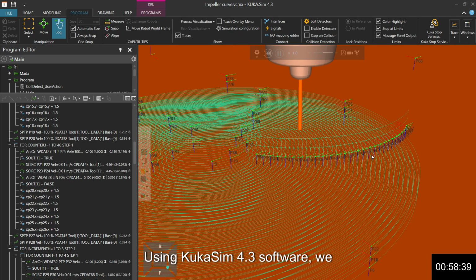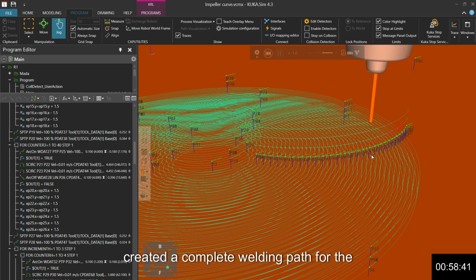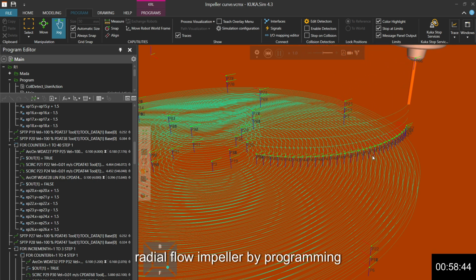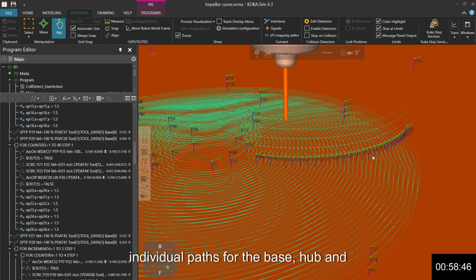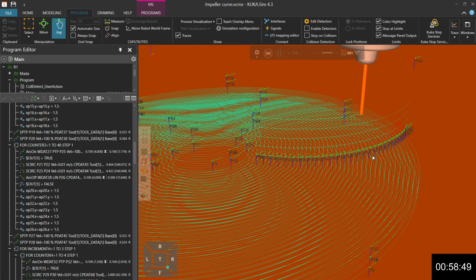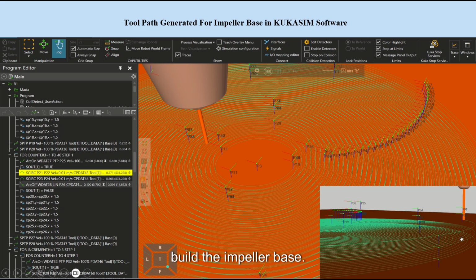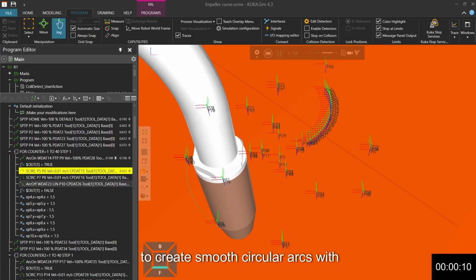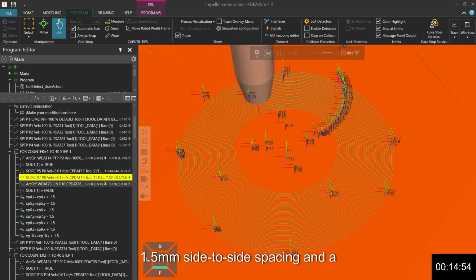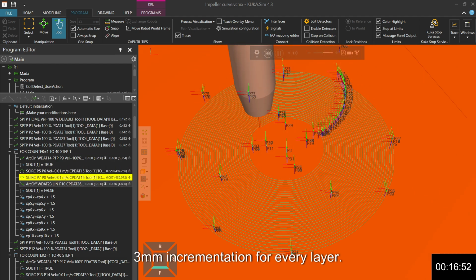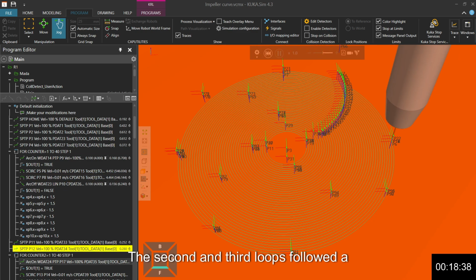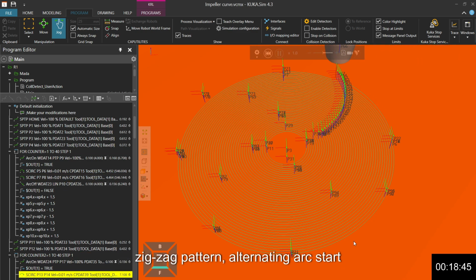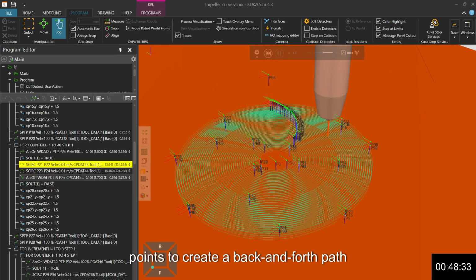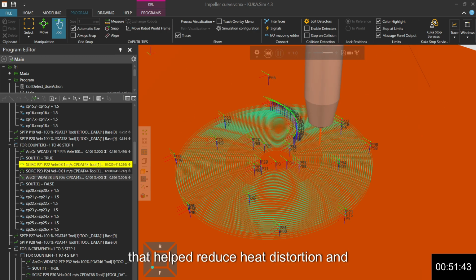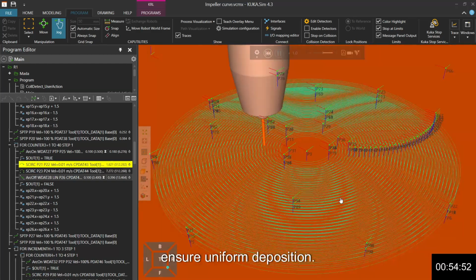Using KUKA Sim 4.3 software, we created a complete welding path for the radial flow impeller by programming individual paths for the base, hub, and blades. 3 welding loops were programmed to build the impeller base. The first loop used circ commands to create smooth circular arcs, with 1.5 mm side-to-side spacing and a 3 mm incrementation for every layer. The second and third loops followed a zigzag pattern, alternating arc start points to create a back-and-forth path that helped reduce heat distortion and ensure uniform deposition.